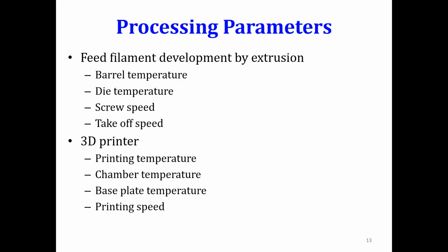Based on that, you can have an initial start and then go on fine tuning, so that you will have a good flowability of the composite blend, which will come in the form of wire. And then the wire diameter is modulated based on the screw speed and the takeoff speed. It is just like inducing a tension while drawing the wire out of the die. This should be consistent enough so that you will have 1.75 mm plus or minus 50 microns or 2.85 mm plus or minus 50 microns, which is pretty much achievable using the available extruders made in India.